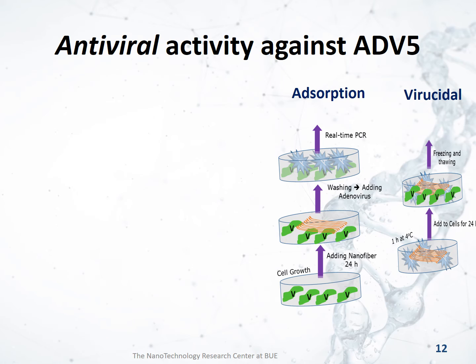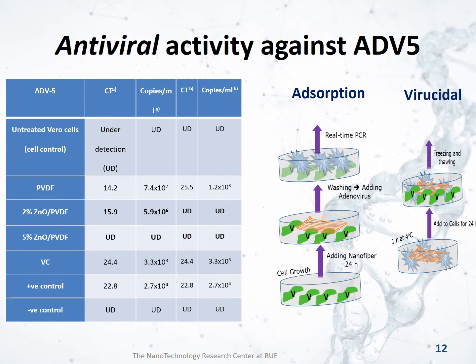In our antiviral activity test against adenovirus type 5, we applied two different mechanisms: the adsorption mechanism and the virucidal mechanism. And we noticed that with zinc oxide loading at 5%, it worked in both mechanisms, while with 2% zinc oxide, it did not work in the adsorption mechanism, but only worked in the virucidal mechanism.